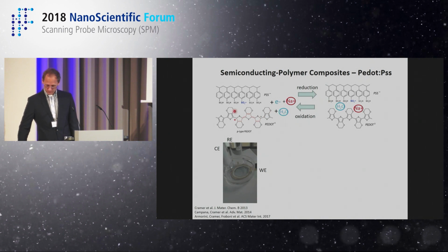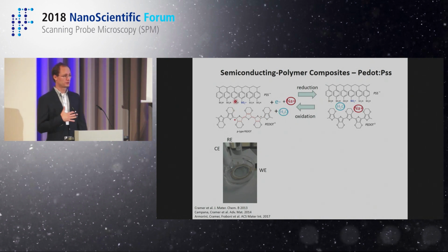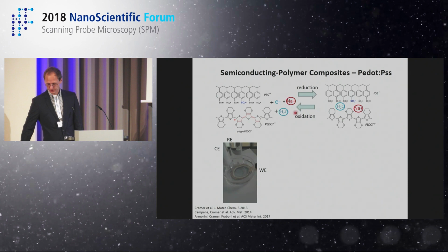Now, for a semiconductor, it's of course relevant, as I've shown you in the transistor, to modulate the amount of charge carriers in your semiconductor in order to have a modulation of the current. And you can do this in a so-called electrochemical way, by reducing or oxidizing your materials. So when you go in the reduction direction, you add an electron that fills the hole charge. Of course, you have to stay electrostatically charge neutral, so you also introduce an ion into the whole system, and this would be, let's say, the composite that is not conducting anymore. Okay, so you have these two states, a conducting and a non-conducting state.